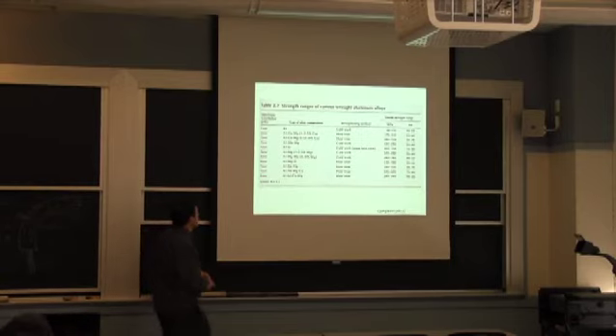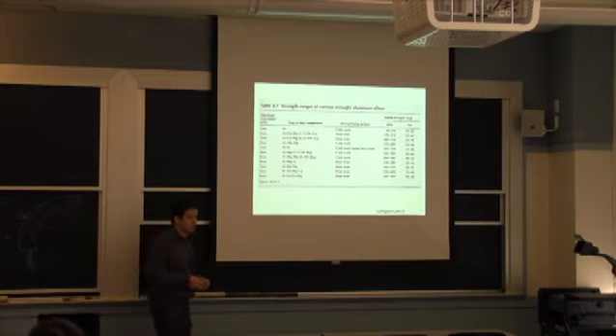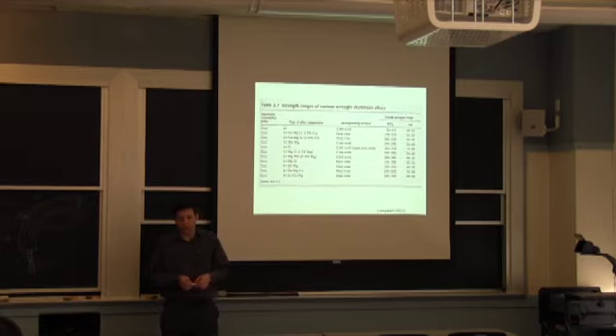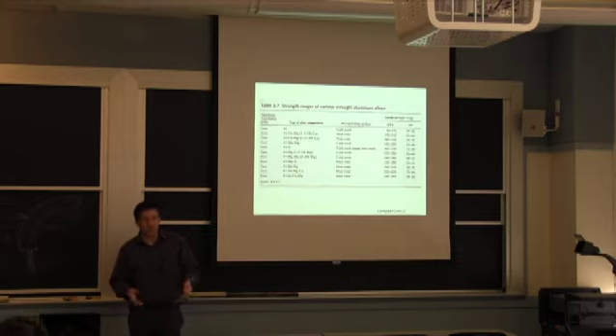It's organized where the 1,000 series is the most pure level of aluminum. It's the one that's electrically more conductive. It's also the most resistant to corrosion. One of the reasons it's resistant to corrosion is there are no precipitates, there are no inclusions in the material that will act as preferential sites to start a corrosion. As you know, aluminum gets its good general corrosion resistance from the natural passive layer that builds on it. And in the last lecture, I showed you the Pourbaix diagram, where this only works nicely between a pH of 4 and 8 or 9. If you're outside that range, you're at risk for accelerated corrosion.